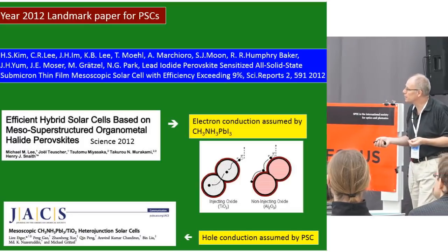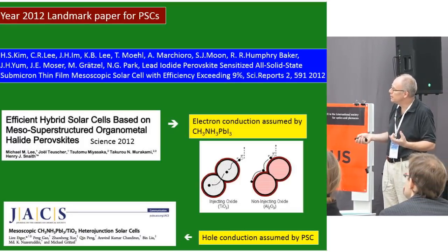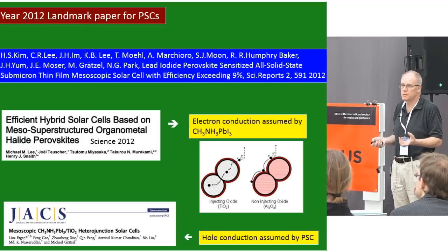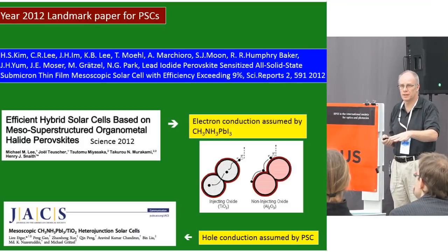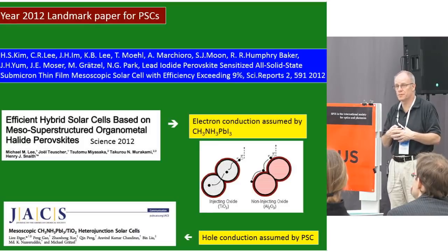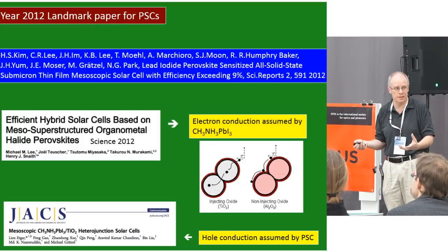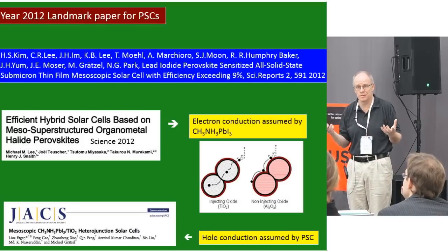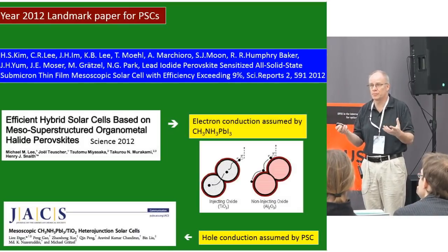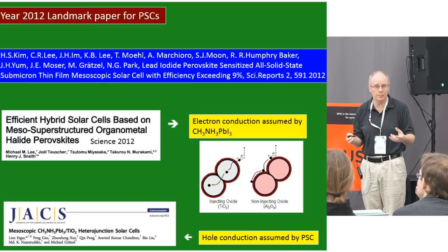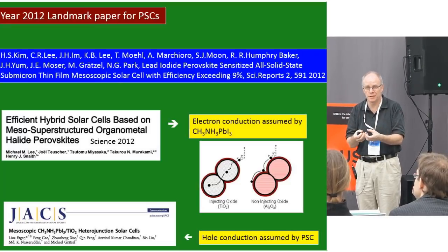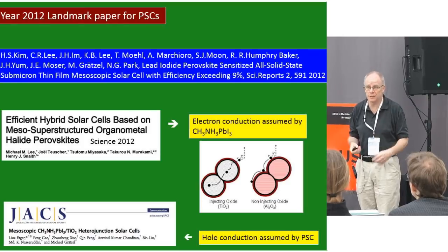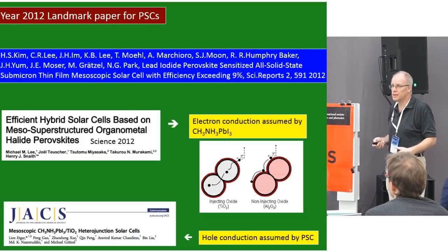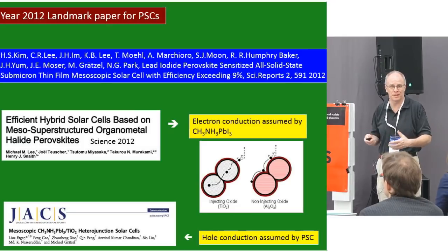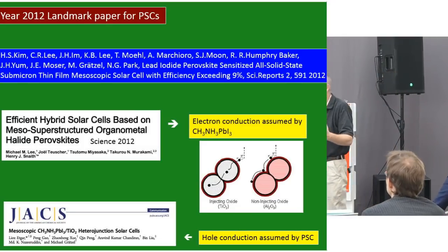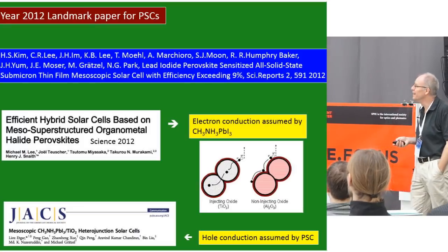Lioz Etgar was with Michael Grätzel at the same time. He's from Israel. He showed that I don't even need to use spiro. I can just put gold on top of the perovskite, and it also works. So the holes are also transported efficiently by the perovskite. That tells you that this is not just a dye-sensitized cell. The perovskite itself can work like that. And we can prepare it like we prepared it in the kitchen. It's solution processed. So that created a lot of excitement. And I think last year we had 5,000–6,000 papers published on perovskite. So it's a tremendous area and very challenging to be in.